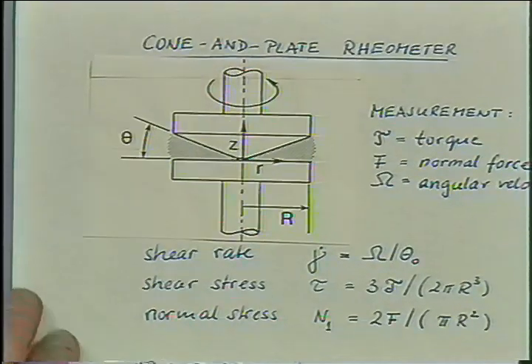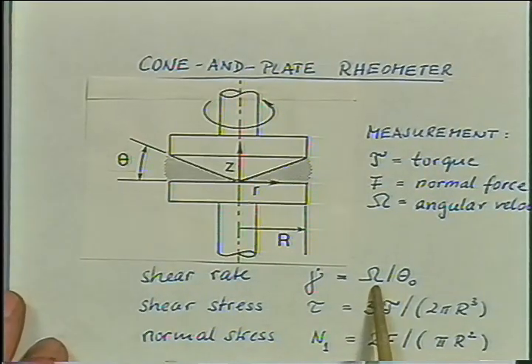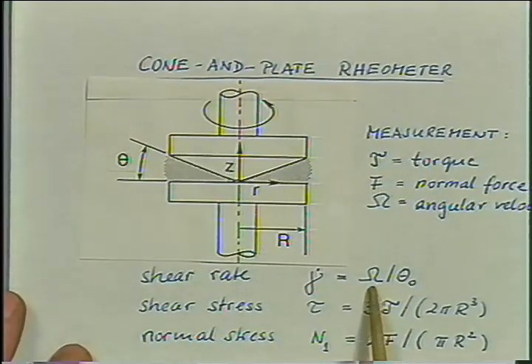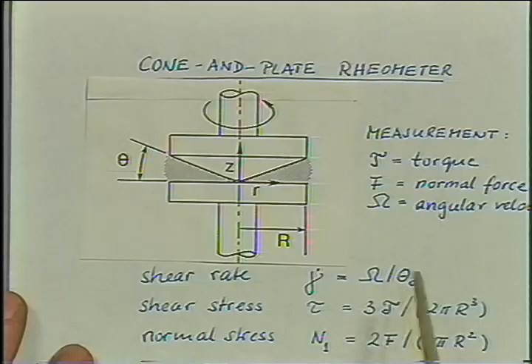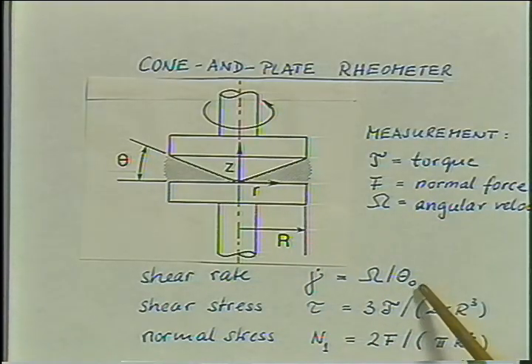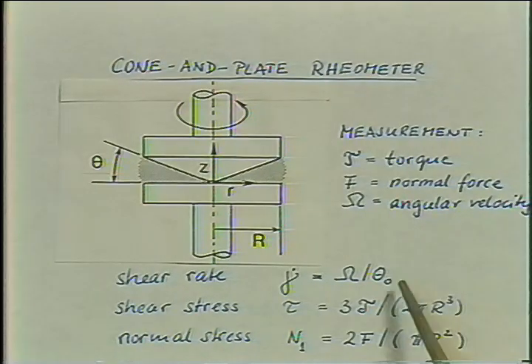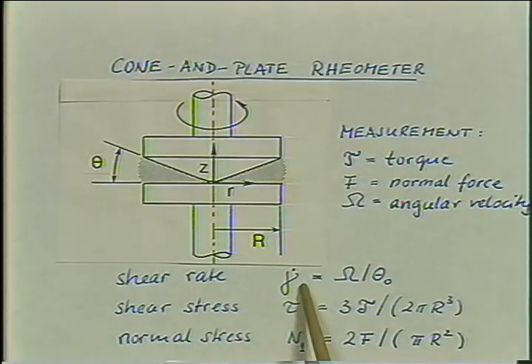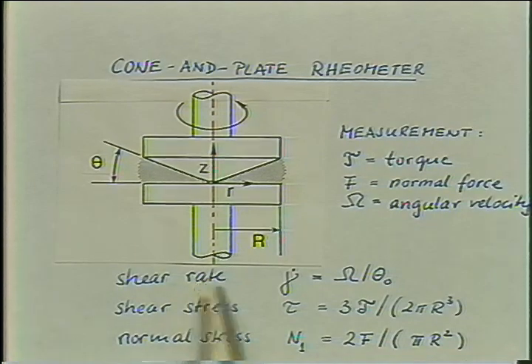We measure the speed of rotation of one of the surfaces divided by the angle of the cone, which is about 0.1 radians for most systems in that order, and we immediately get the shear rate. The shear rate is uniform throughout the sample. It's a homogeneous deformation. We can expose the sample to small and large strains. It's a very nice tool to have.